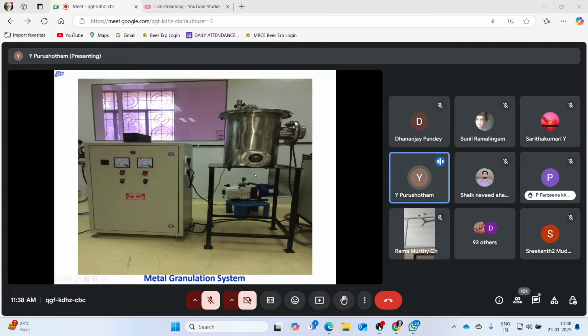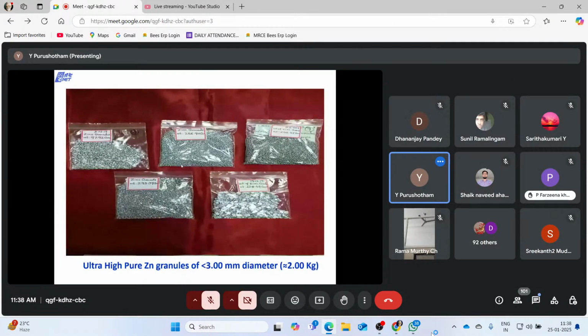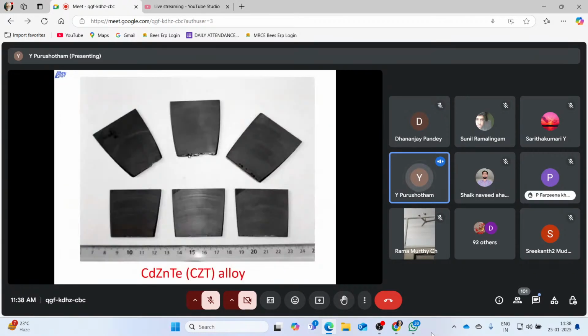We did a number of experiments. Initial experiments failed because the granules were not uniform. Different sizes were there, and sometimes a lot of agglomerates used to come out. We again optimized the process parameters, and finally we got less than 3 mm diameter high pure zinc shards. With this, we prepared around 2 kg of shards of less than 3 mm diameter. This was the target given by our funding agency, and we supplied this to IGCAR for their CZT alloy preparation for detector applications. So like this, we successfully prepared the 7N grade high pure zinc for detector applications.